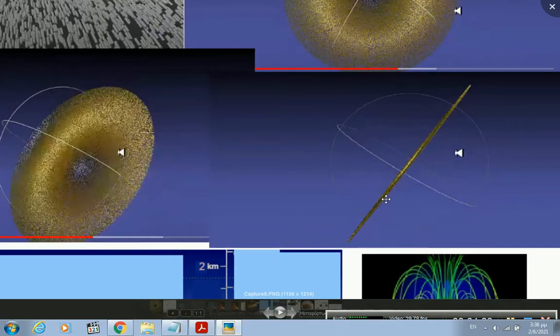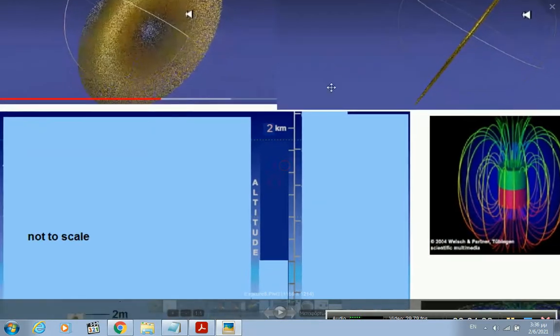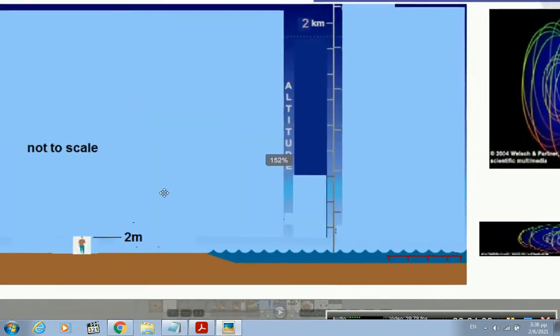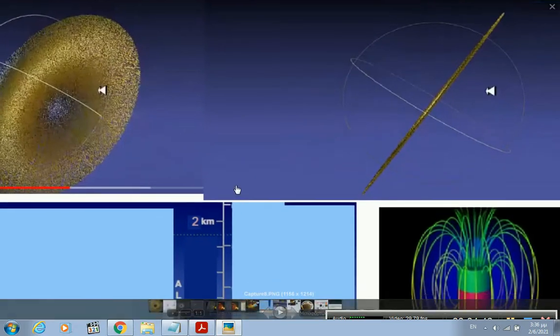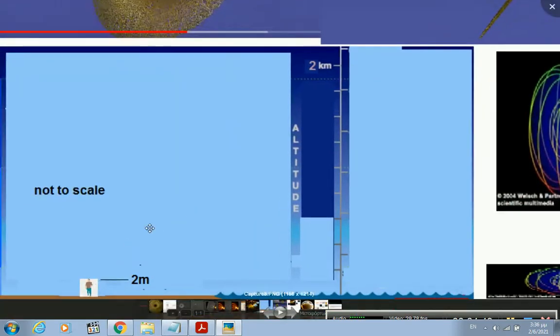From there they imply that this is only a 2D surface, which is true to some extent: it is a 2D cross-section projection of the incident field on the ferrocell surface. But there is some difference, because the nanoparticles are 10 nanometers and the thickness of this thin film is 10 microns. In the older generation of ferrocells it was 25 up to 50 microns.